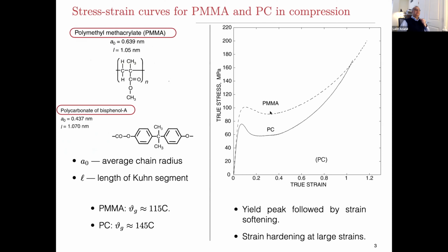So in a compression test, this is what the stress-strain curve looks like. You have a yield peak, it softens, and then it hardens quite dramatically. PMMA is about 100 megapascal yield strength, if you will, in compression, and polycarbonate is about 80 megapascal. So the yield peak is important in these materials.